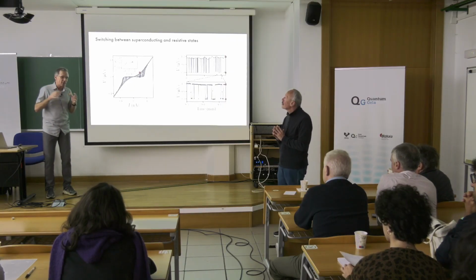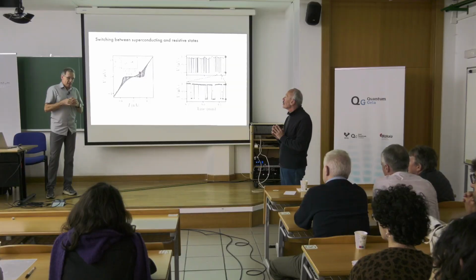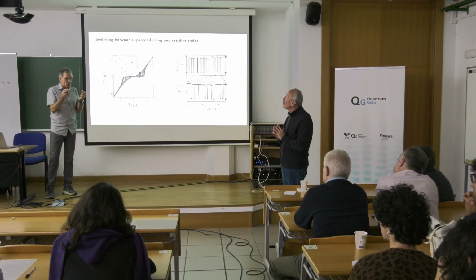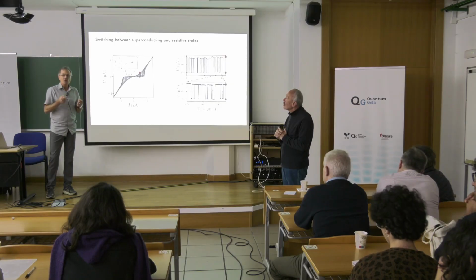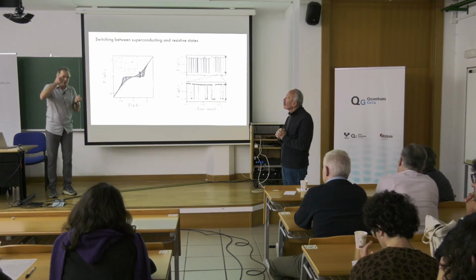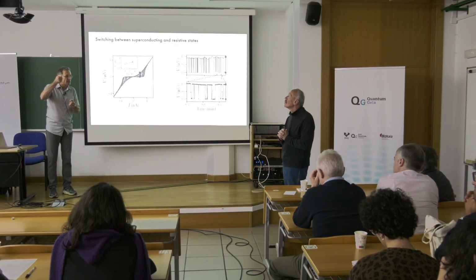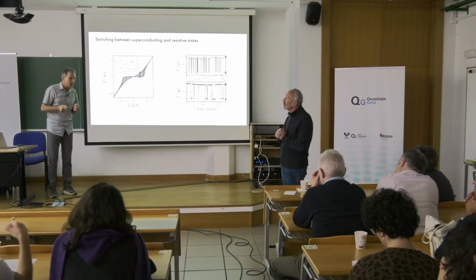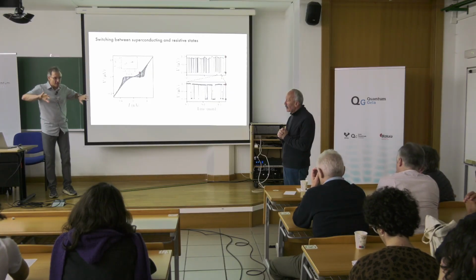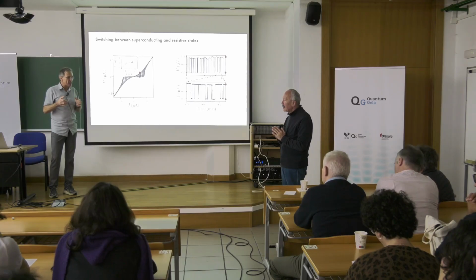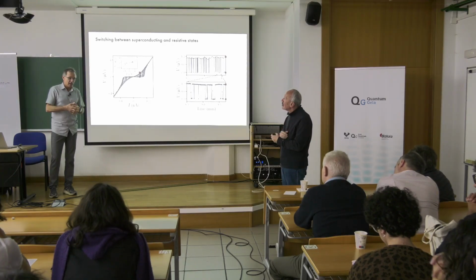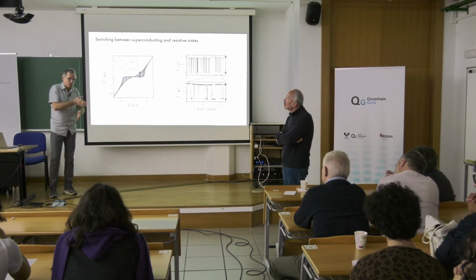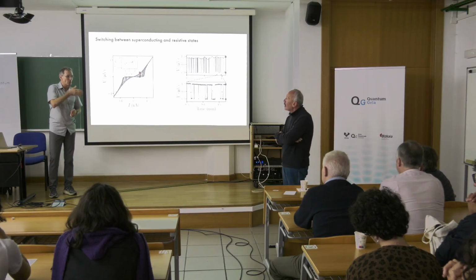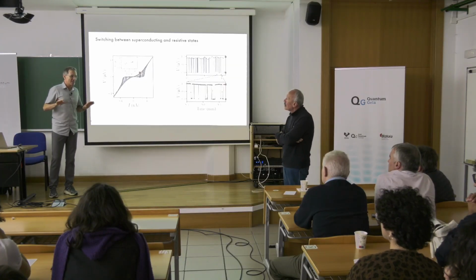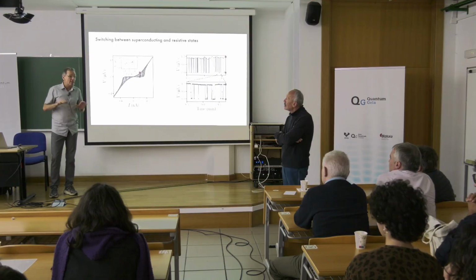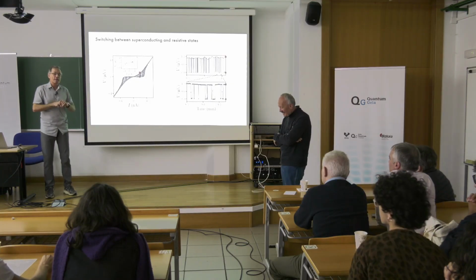Because in general, the transition temperature depends exponentially on the strength of electron interaction, and you have a large exponent, a large thing in the exponent which you don't really know, and there is Coulomb repulsion, and then phonon attraction and so on, and that's what makes it almost impossible to predict, not even the transition temperature, but which material would be superconducting and which not. Well, it's possible a posteriori after we know.